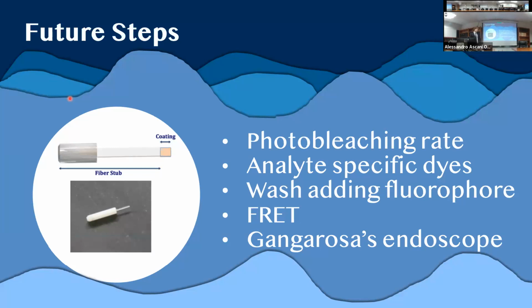Further, I mentioned earlier the washing step. While we are adding the shell onto the particles, how we've been washing them so far and removing the liquid outside, we have just been replacing it using plain ethanol. This creates a chemical gradient that, at the moment in which the particles do not have a shell, brings to the leaking out of fluorophore over time.